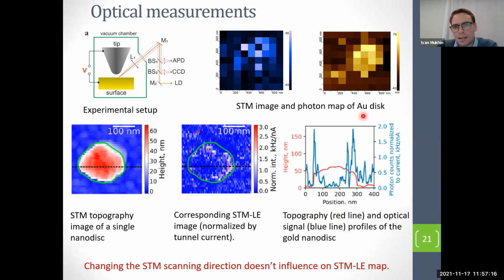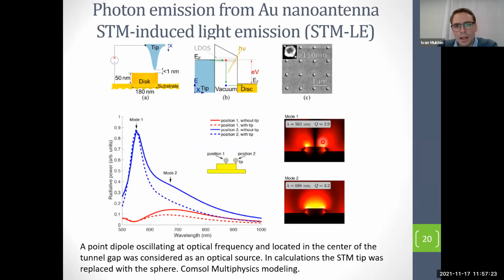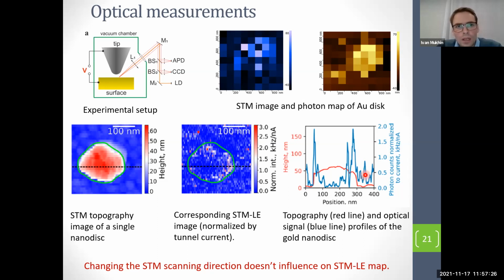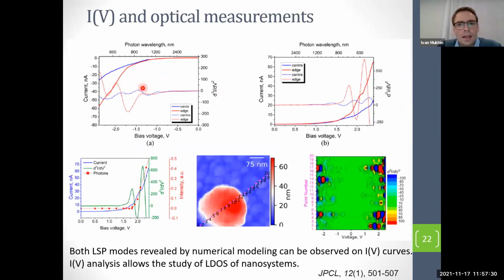So these experimental results correspond very nicely to this numerical modeling. And at the end of this part of the talk, I would like to present again the IV curve study of the nano-antenna. We positioned an STM tip in the center of the nanodisk and at the edge of the nanodisk, and measured IV curves. Look at the red one. The red one is at the edge of the nanodisk, and you clearly see on the second derivative two features which correspond to about 590 and 690, which corresponds well to this numerical modeling.